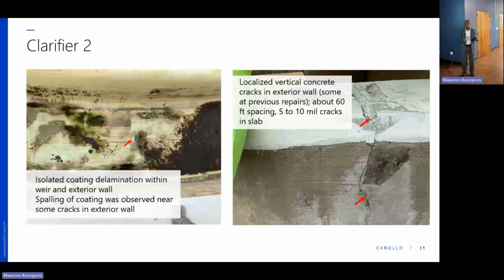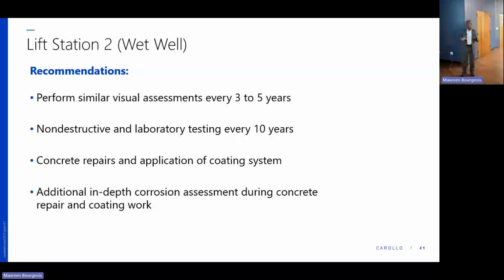For the lift station, since that's an aggressive environment, we also recommend that when we go in to do the concrete repairs, we should look at an additional in-depth corrosion assessment to see what we need to do further, if we need to protect the structure further, just to extend the service life of the structure for the long run.